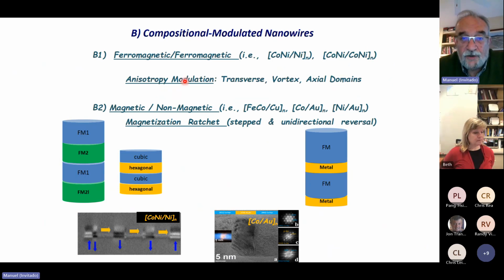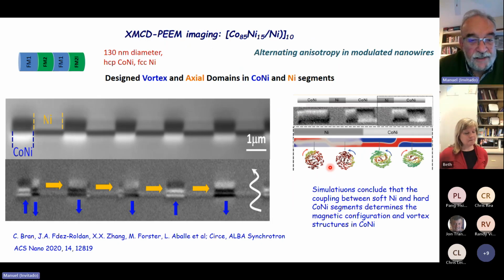And finally, the compositional modulation in the nanowires. The objective is to have first a segmentation with different segments having cubic or hexagonal magnetic anisotropy, depending on whether the crystalline structure is different. The second modulation can be ferromagnetic and metal. Well, for the first modulation in composition, here we have a topographic image where we have cobalt nickel and nickel segments, where they are very well differentiated from cobalt. The transition from one to the other is very sharp.